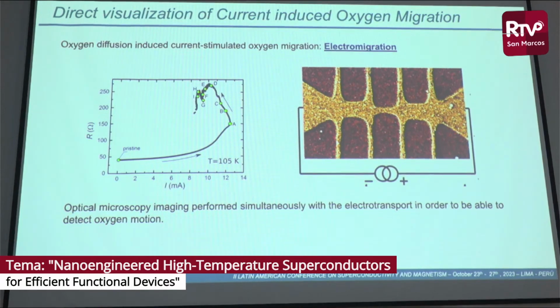And in this experiment, what we did is to move the oxygen in the system by applying a current through the system. And with this current, we induce motion of the oxygen in the system, which would change the oxygen content and the resistance.